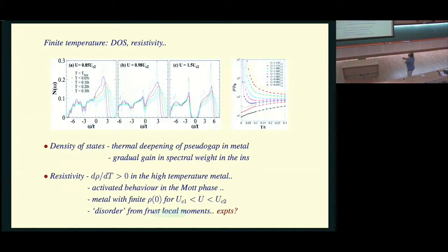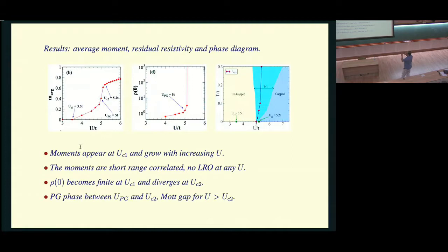Okay. So even if I don't manage to get through all the molybdate story, this is an instance of, if you wish, a spontaneously broken translation symmetry due to the frustrated, okay, due to the emergence of quasi-random magnetic moments over a certain window here, leading to a finite resistivity phase.